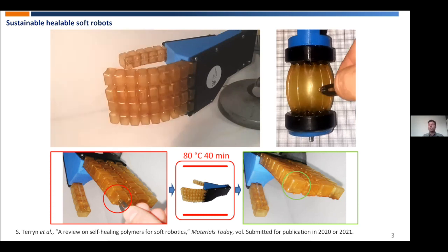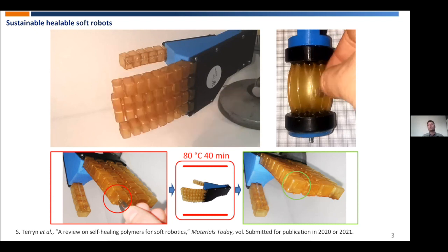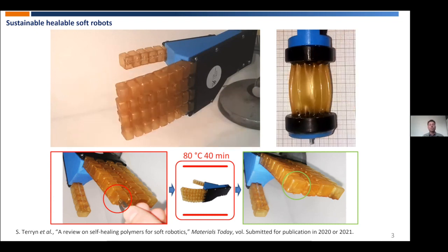And therefore, they can heal from small damages, but also large damages like the cuts you can see there in the videos. And for these particular prototypes, the healing works by applying heat. So we heat these hands or these muscles to 80 degrees for only 40 minutes. And then these damages, they are completely healed. So these systems are, again, as good as new. So this means that the healing can also take place for multiple times, and therefore the lifetime of these components can be increased a lot in future applications.